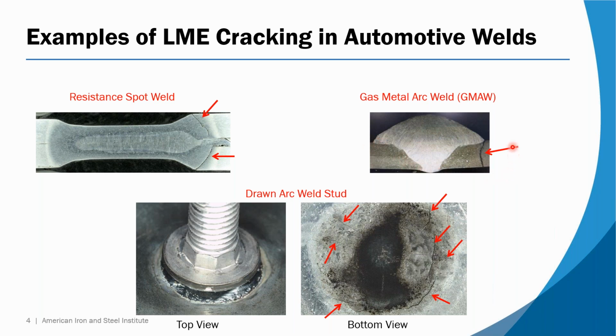We found a way to cause that crack in gas metal arc welding, so it could happen there too. And even in drawn arc welding, where you put these studs all over the car, if you flip the panel over - this is the back side of this sheet down here - you can see there are cracks in the peripheral direction and also radially extending outwards. So anyway, we can't ignore these cracks, and that's what this talk is about.